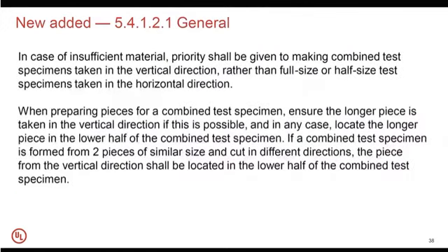In 5.4.1.2.1, there is some general information for the specimen. So in case of insufficient material, priority shall be given to making combined test specimens taken in the vertical direction rather than full-size or half-size test specimens taken in the horizontal direction. As well, when preparing pieces for a combined test specimens, there is the need to ensure the longer piece is taken in the vertical direction if this is possible, and in any case locate the longer piece in the lower half of the combined test specimens.